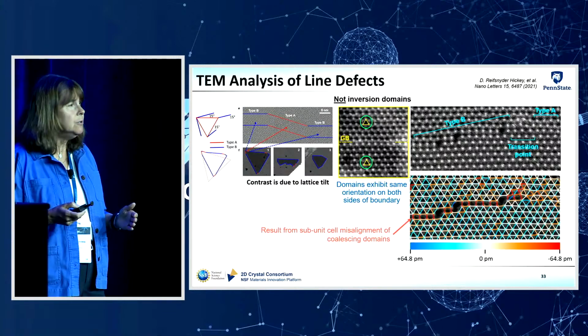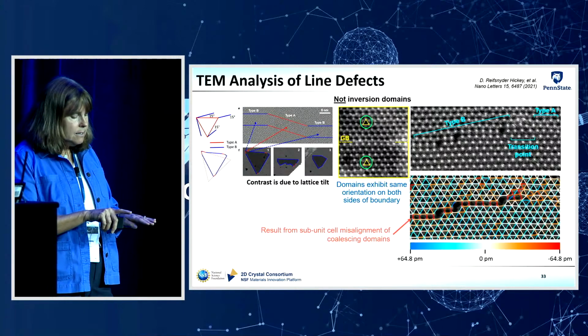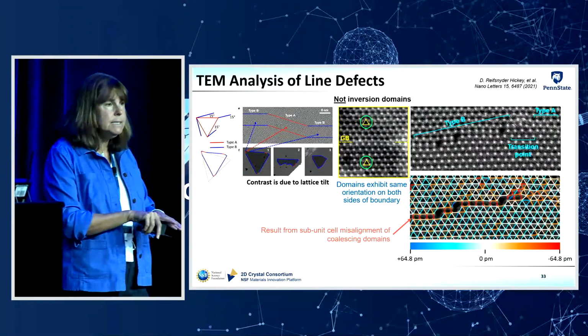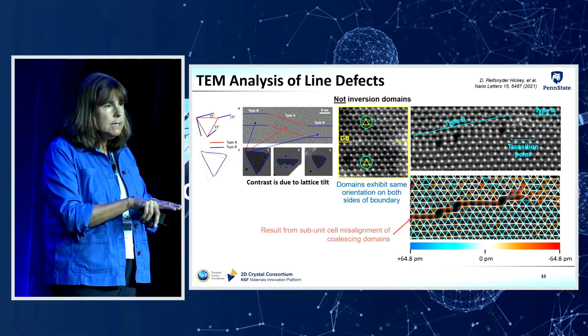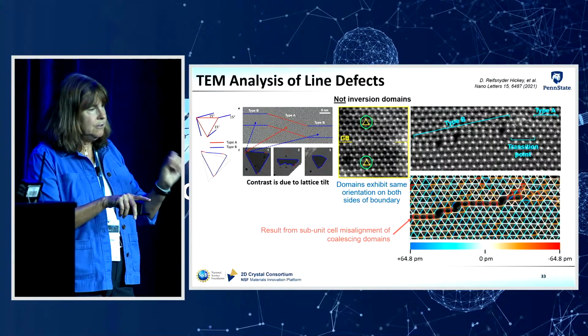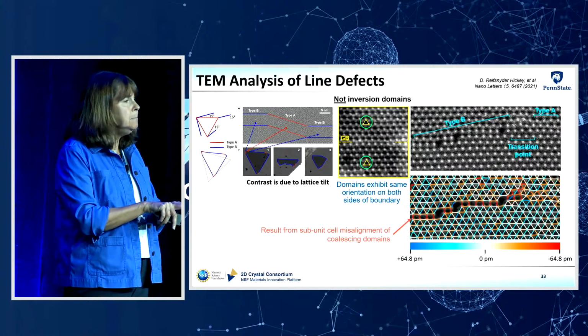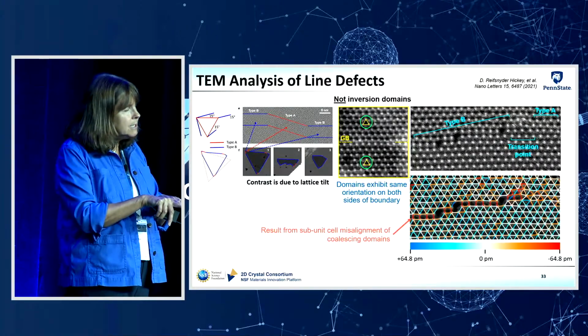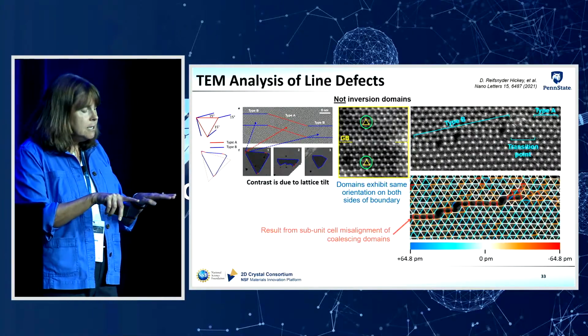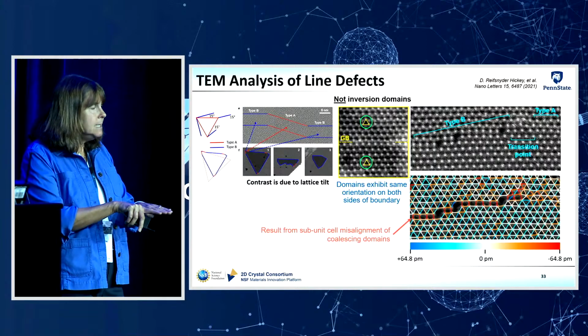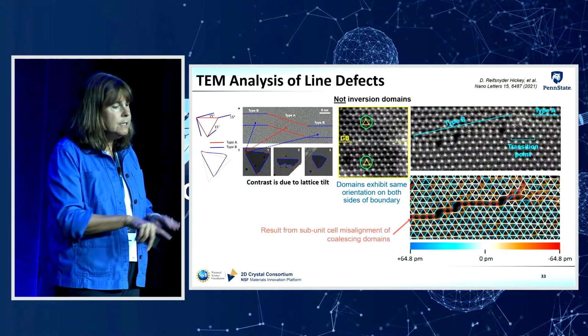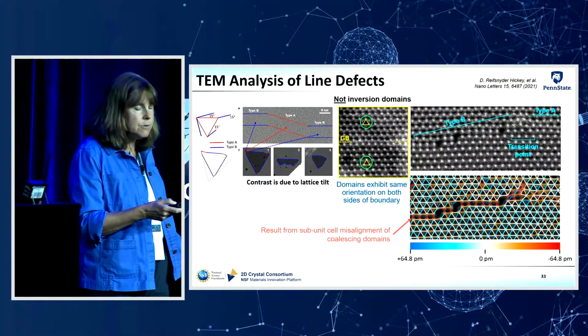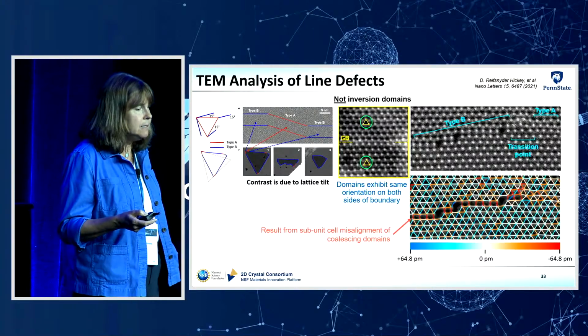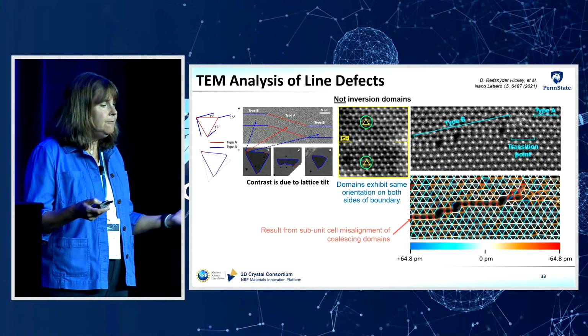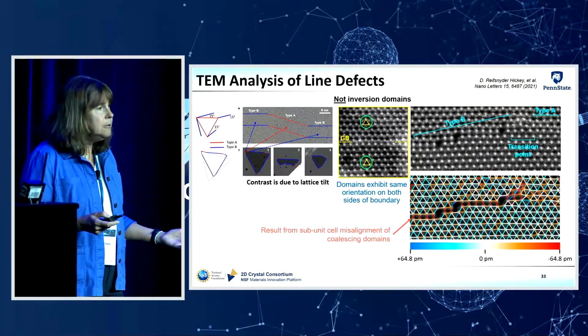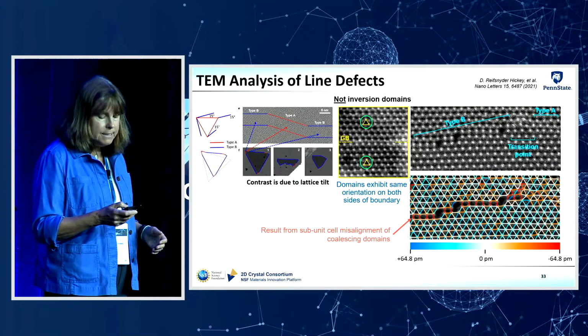Instead, these are translational line defects. So they're defects that arise when you have domains that are oriented in the same direction, but they're slightly offset, even by like a subunit cell length distance. So they're just slightly offset from one another. And as a result, you don't have a perfect stitching together of the lattice. You have some vacancies that are present, and that gives rise to these translational line defects. So this is another type of defect that is present in monolayer films, in addition to the inversion domains that I mentioned earlier.